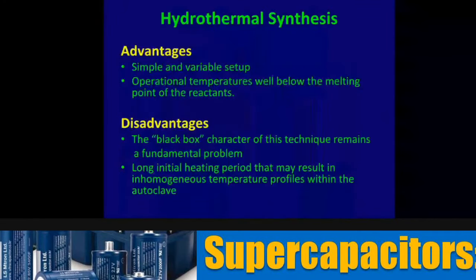The other method is hydrothermal synthesis, where the reactants are in the form of a liquid. They are put in a sealed container and the temperature is increased so that a hydrothermal pressure is developed, and that permits the reaction to take place. Again, it's a very simple setup. Operation temperatures are very small. Maybe you can operate at 100 to 150 degrees.